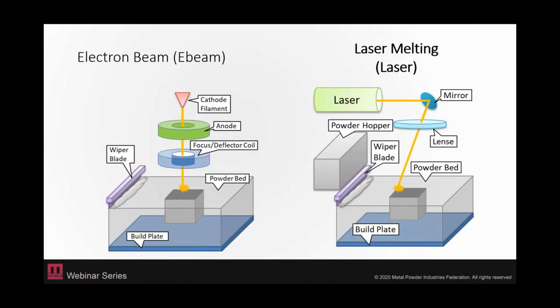The electron beam works like an old CRT tube TV. The electrons get pulled down using a differential charge, and their trajectory is guided by a magnet. So it's really fast. Because we're using electrons, though, we have to do this process in a vacuum. And that's going to come into play with our powder quality, which we'll get to.